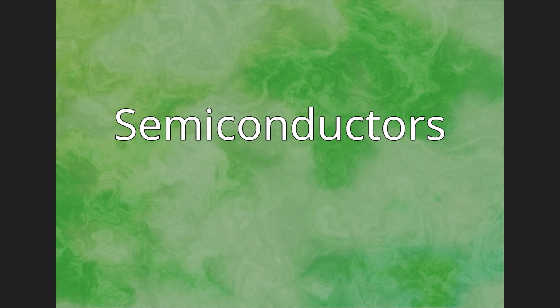Semiconductors. The process of metal organic vapor phase epitaxy (MOCVD) entails pyrolysis of volatile organometallic compounds to give semiconductors, hard coatings, and other applicable materials. The reactions entail thermal degradation of precursors, with deposition of the inorganic component and release of the hydrocarbons as gaseous waste. Since it is an atom-by-atom deposition, these atoms organize themselves into crystals to form the bulk semiconductor. Silicon chips are produced by the pyrolysis of silane, SiH4 → Si + 2H2. Gallium arsenide, another semiconductor, forms upon co-pyrolyses of trimethyl gallium and arsine.